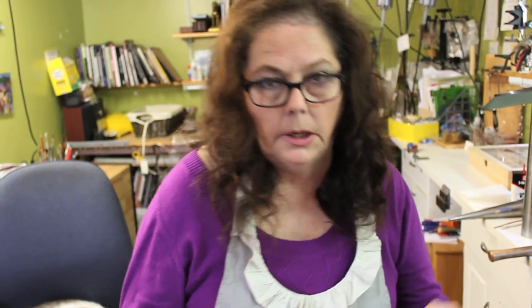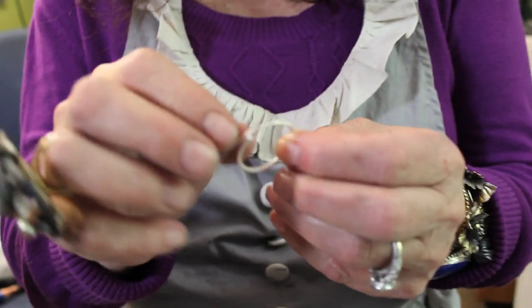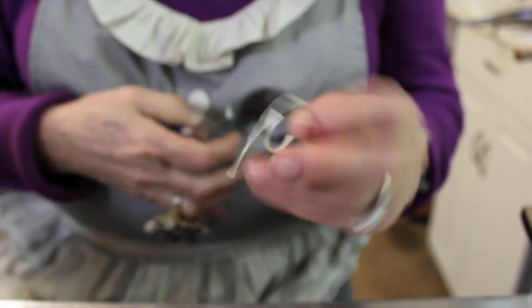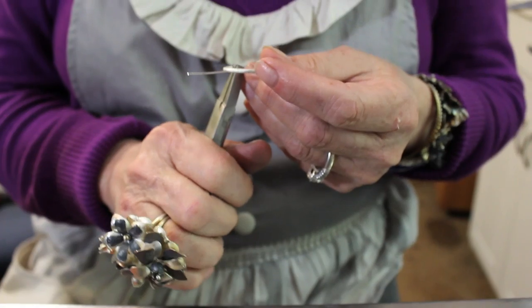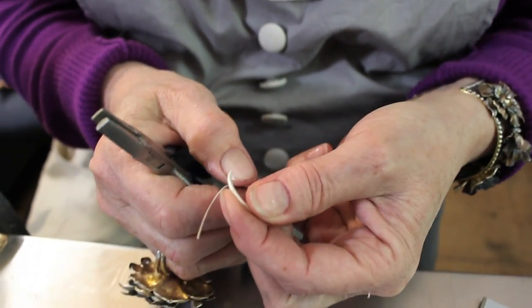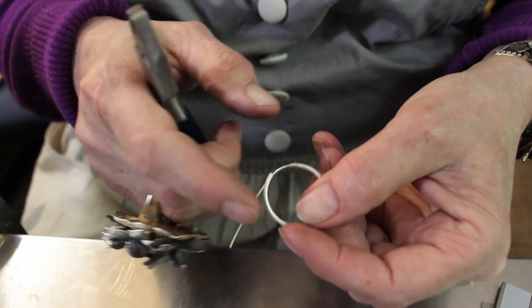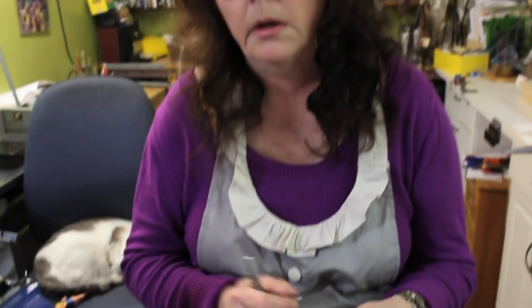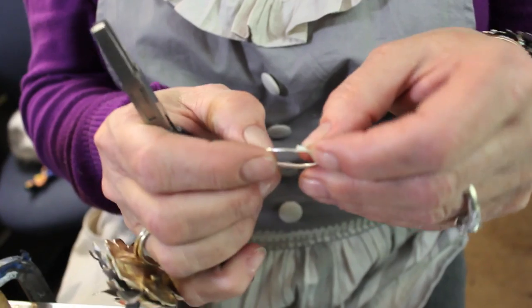I know I'm not looking at it, I'm sorry. I'm not going to clean this up, but the wire's in there now. And we want the ear wire to follow the natural curve of the piece. So I'm using a plier that's got a rounded edge on one side and a square on the other, and I'm just going to shape it a little bit. You can open it up this way. One thing I do want to say about when you're making this hollow tubing earring — you probably should boil it in baking soda because the pickle gets inside here. Either that or run a thin stream of water down in here to try to rinse it out thoroughly. And move this back and forth a little bit — it's not a bad idea to work-harden it because that soldering process annealed this.